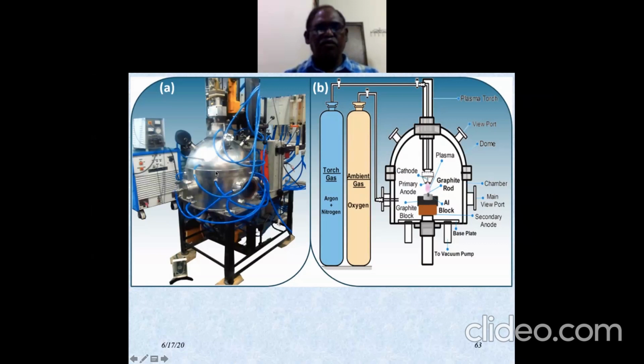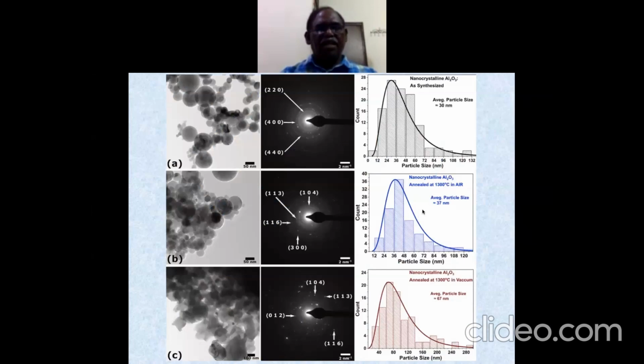So what we have done over here, we have taken aluminum powder and mixed it with graphite for doping carbon, and then a plasma is generated over here, okay, and then oxygen gas is let in over here. So these ions, aluminum and carbon, then react with oxygen. Some of the carbon also reacts to give carbon dioxide, but if you control the amount, still some carbon remains inside, and you get the aluminum oxide carbon. And this shows the very good nanoparticles over here, and this also shows the particle size distribution.